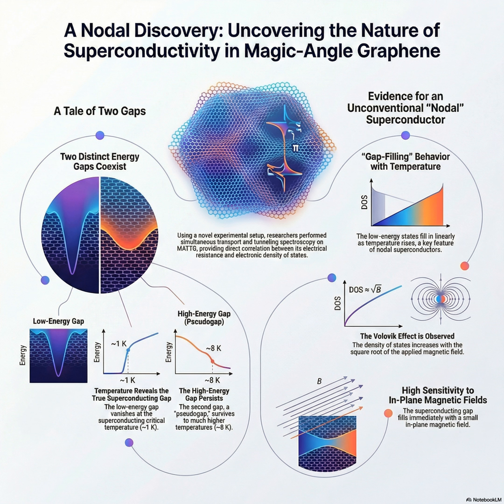But a nodal system has those holes. It has the holes, so the minute you add even a tiny bit of heat energy, those quasi-particles can immediately start leaking out through the nodes. And is that what the data showed? That's precisely what they found. The zero bias conductance immediately rises linearly with increasing temperature, well before the transition temperature is even reached. That linear rise is the telltale signature of a nodal order parameter.